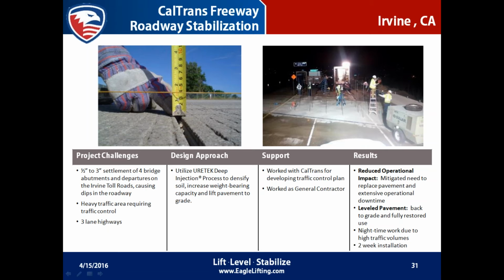Utilizing the URETEK deep injection process to densify the soil, increase the weight-bearing capacity, and lift the pavement to grade, we were able to work with Caltrans for developing a traffic control plan and work as the GC. They reduced operational impact by mitigating the need to replace the pavement. They leveled the pavement by bringing it back to grade and fully restored the use, and they were able to work at nighttime. In order to avoid the high traffic volumes, they were actually able to shut down the lanes without impacting the traffic negatively.